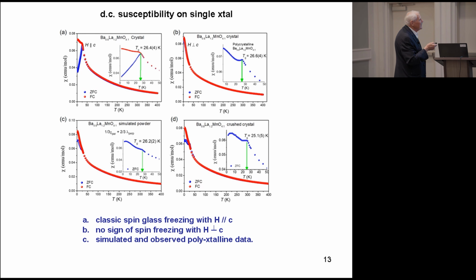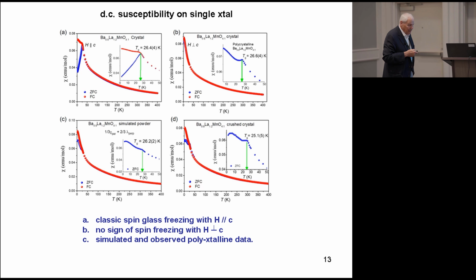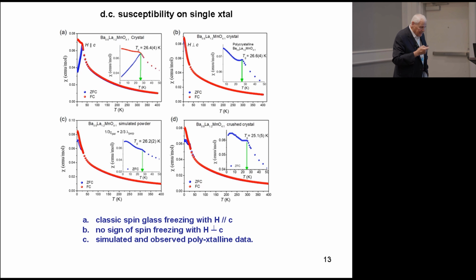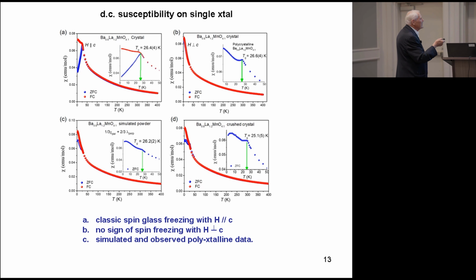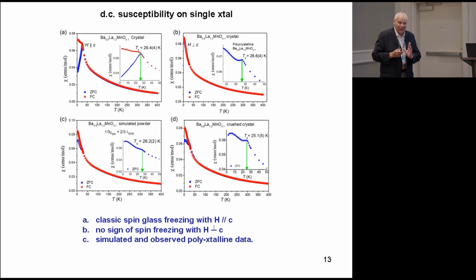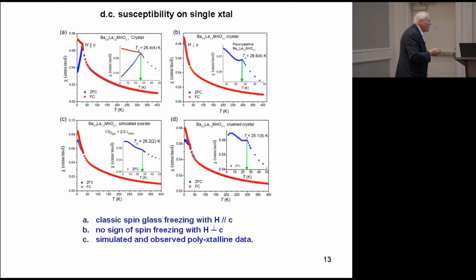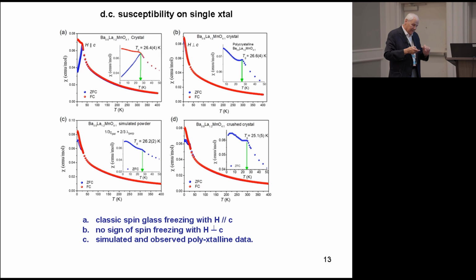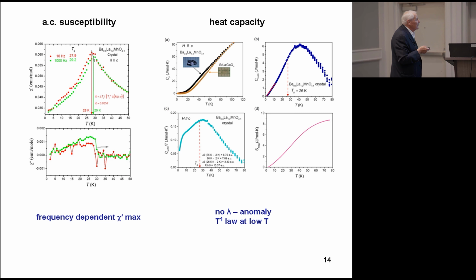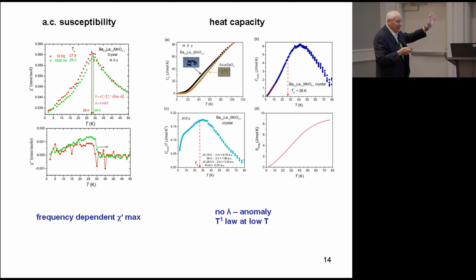Now I just want to say, what's happening here when the field is perpendicular to the c-axis? There's no evidence of freezing, but it's also not really paramagnetic. If you look very close to the base temperature, you see that the curve is supposed to be a hyperbola, it's supposed to shoot up, and it doesn't. There's some evidence that it might be turning over a bit. So this might be evidence of spin correlations now forming in similar directions. For the purists, we have other evidence of the spin glass character: AC susceptibility, frequency fitting, the Mydosh criterion, linear heat capacity at low temperatures, and all sorts of things.